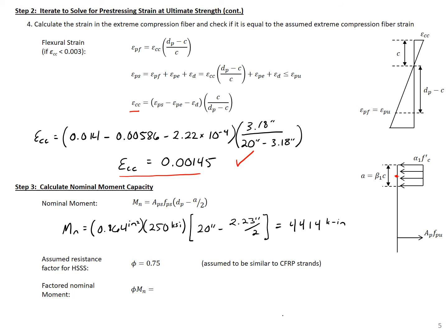The resistance factor phi for high-strength stainless steel has not yet been established. We're going to assume a phi similar to CFRP strands — carbon fiber reinforced polymer — so phi equals 0.75. Both materials are less ductile than conventional pre-stressing strands and failure can be controlled by strand rupture in both cases. Therefore, phi times Mn equals 0.75 times 4,414 kip-inches, giving us a factored nominal moment of 3,310.5 kip-inches for our section with high-strength stainless steel strands.